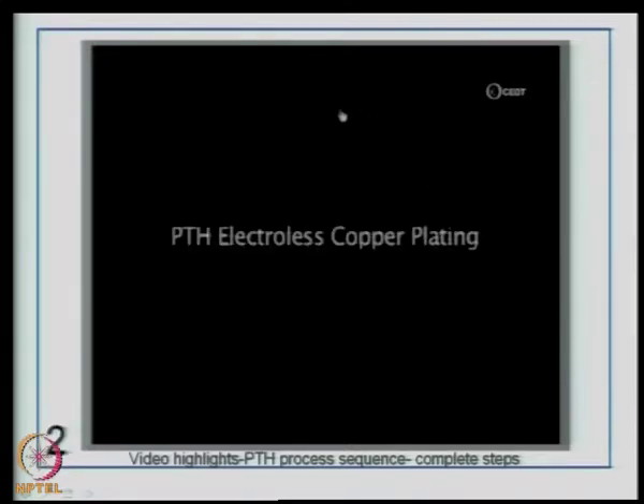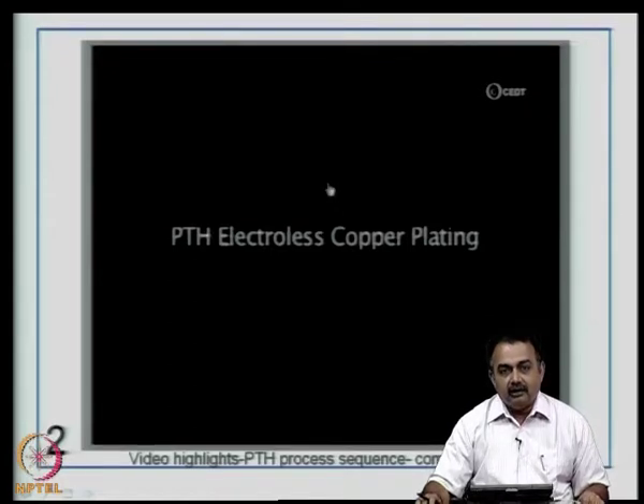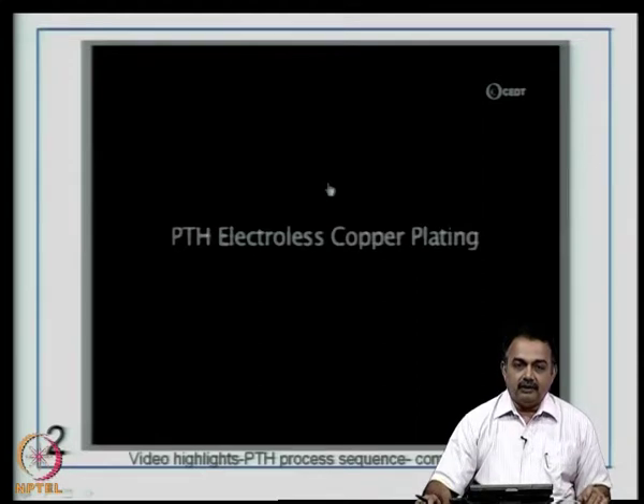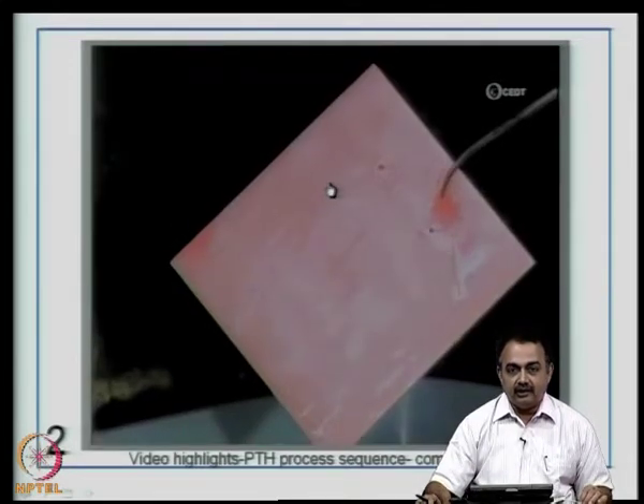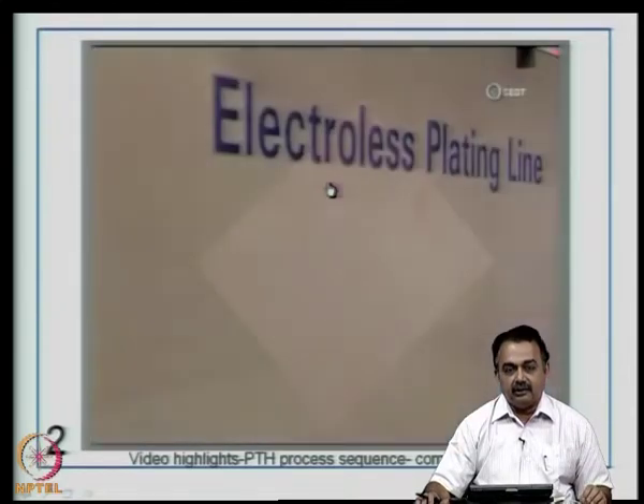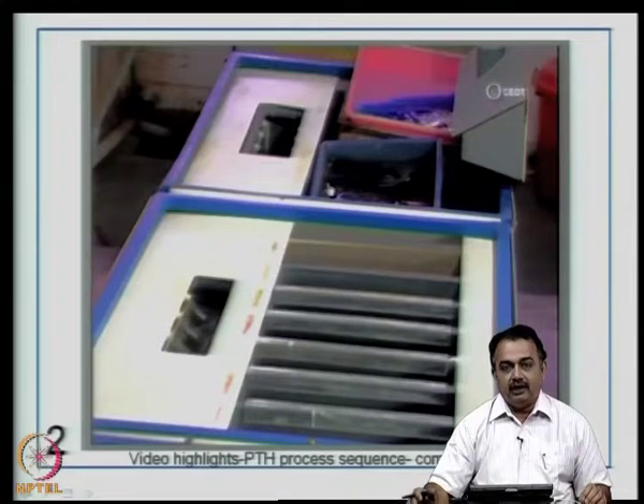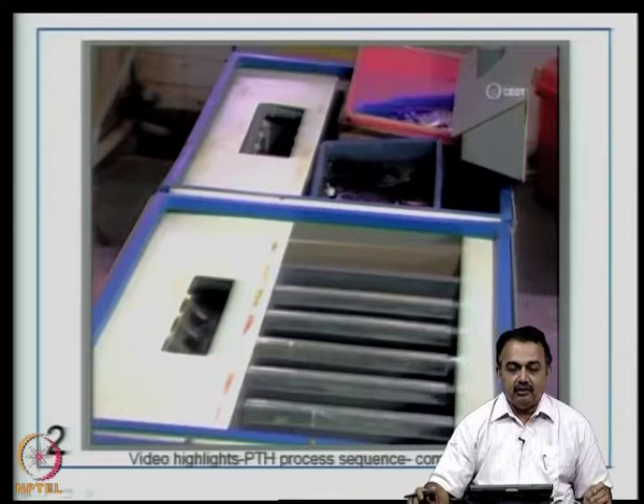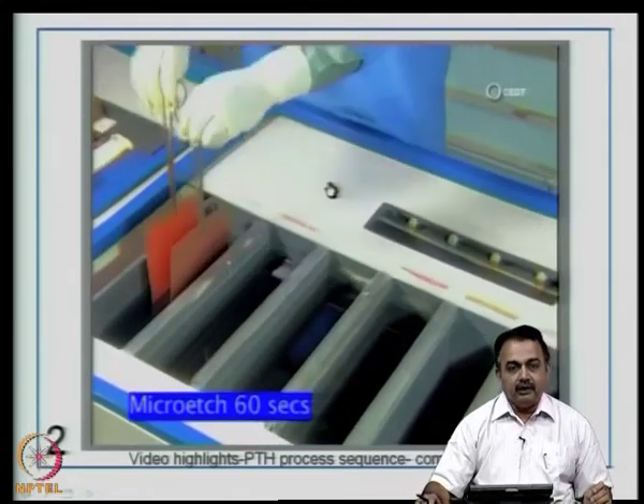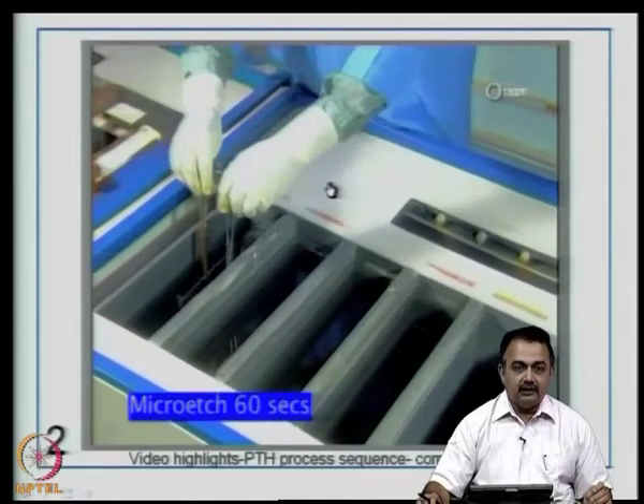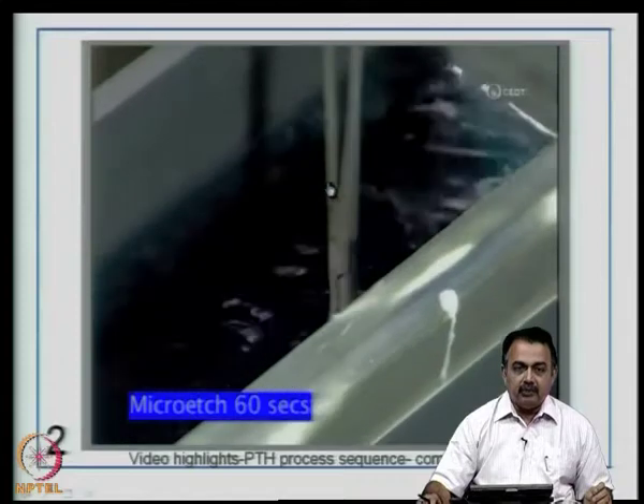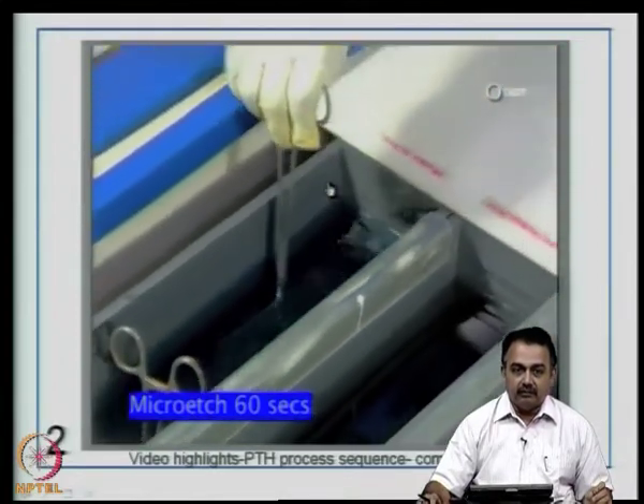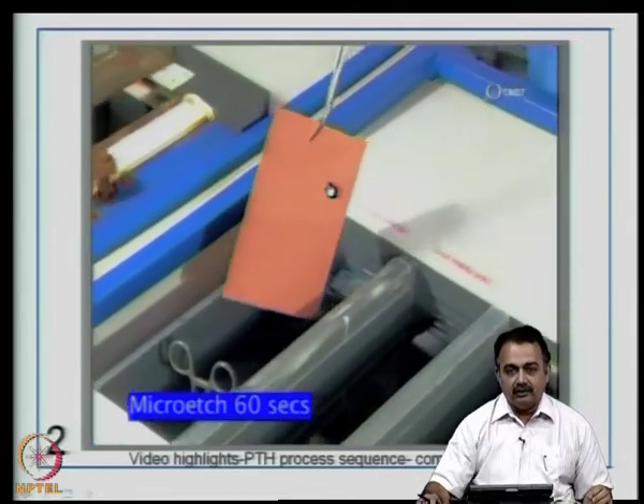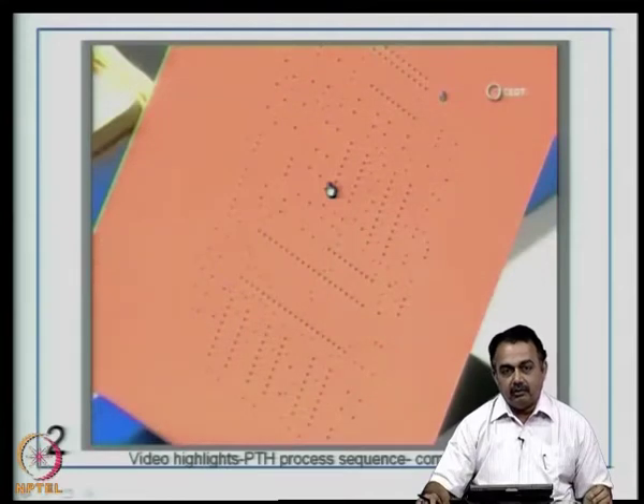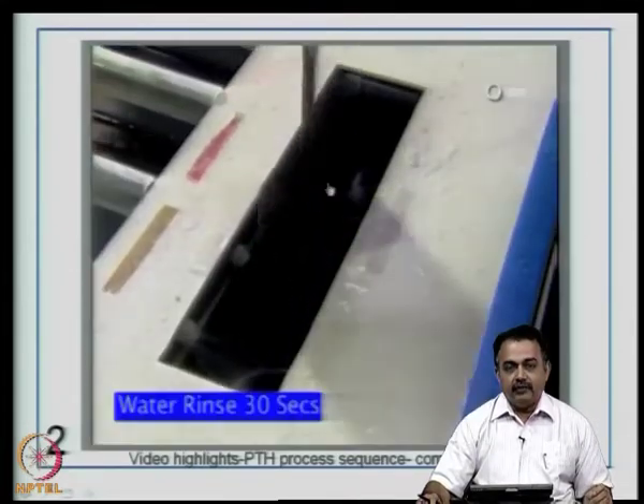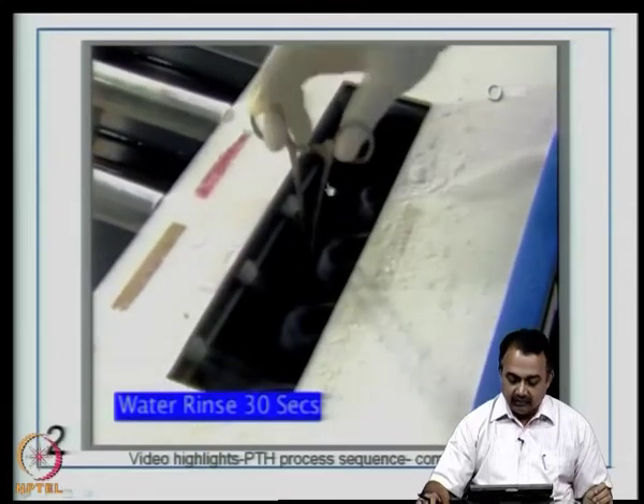Now, we get into the second step of the plated through hole sequence, which is called the electroless copper plating. So, once again I emphasize, we are not using an external DC current here. We are using a chemical reduction process from a copper rich solution and using some reducing agents to deposit copper onto the surface of the board as well as the through holes. Now, before that, if you look at the video, what we are basically doing is a micro etch. This will remove some amount of copper from the surface of the board to the extent of about 1 to 2 microns. This will provide more roughness, more surface area for the imaging process to happen in a good manner.